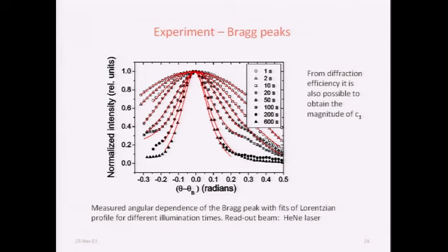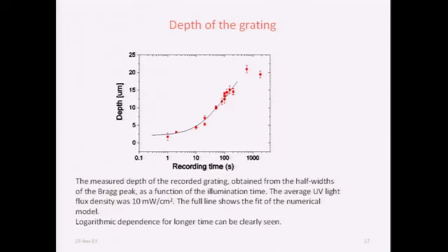So now the experiment looks like you'd expect. And from fitting to the peak widths, we can get how the depth of the grating progresses with time. And we see that it really goes, this is logarithmic scale, so after initial time, it really goes logarithmically, like I have explained before.